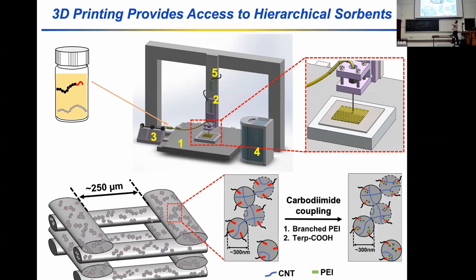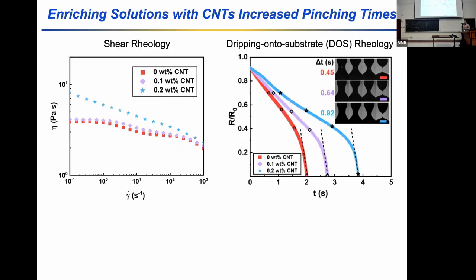And because we haven't changed the formulation of the solution too much, we could then go through the exact same type of post-synthetic modification of these membranes or of these structured filters. So the first thing that I'll point out is that you can't just print the solution on its own. If you try and do that, you make a little bit of a mess.